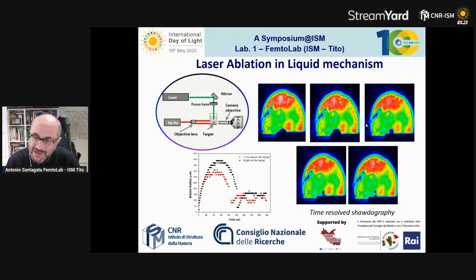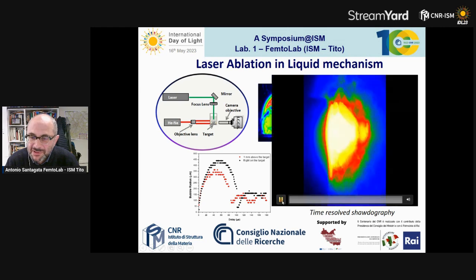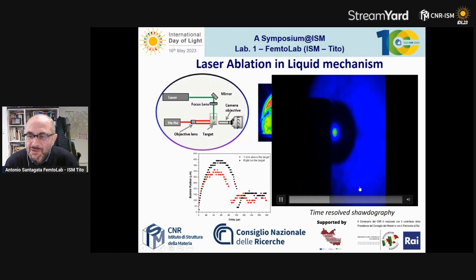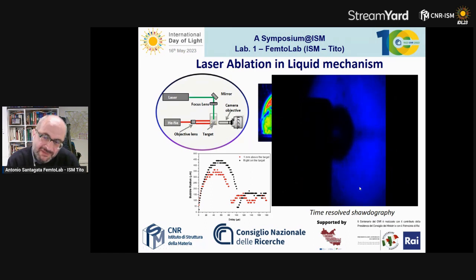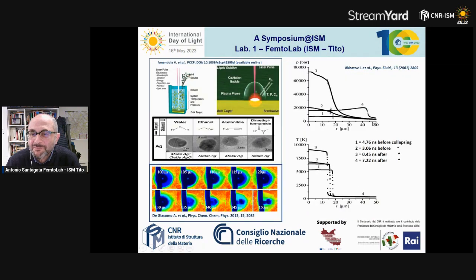And actually, we have an oscillation of the bubble, and you can see the movie here, where the nanoparticles are formed. But when these are generated, when the cavitation bubble collapses, high temperatures and pressures are reached. So in terms of pressures, we can reach gigapascal and temperatures of 10,000 Kelvin. So we have high temperature, high pressures, the cavitation bubble collapses, and we have generation of nanoparticles, which can be strongly affected by the surrounding liquid composition.